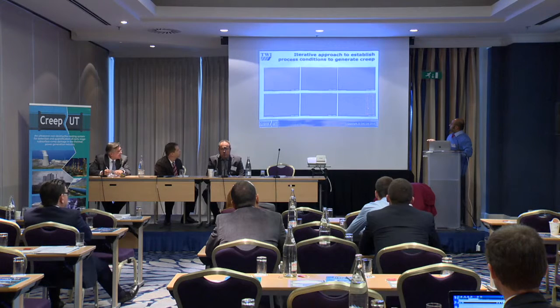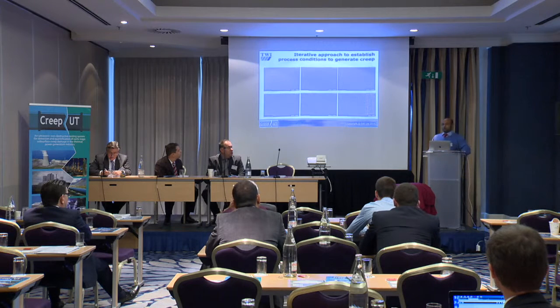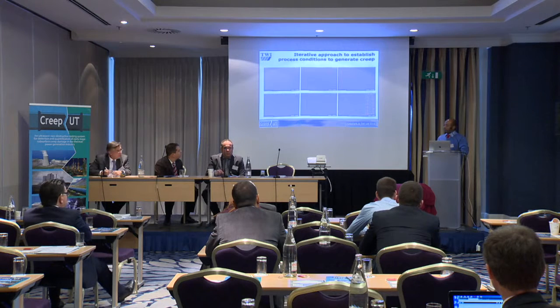So here you can see something that is fairly late stage damage, whereas on this side you can see damage which is much earlier stage. And so that's a fairly representative set of specimens that can then be used for the implementation or checking or validation of creep testing systems, UT, but also other things. For instance, X-ray computer tomography has been implemented using these kinds of specimens.